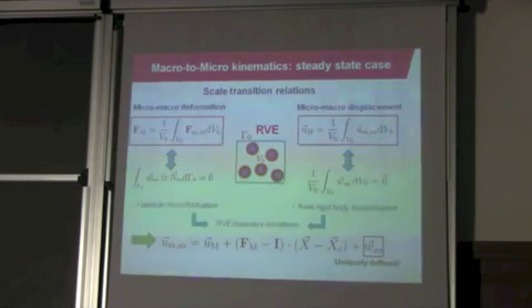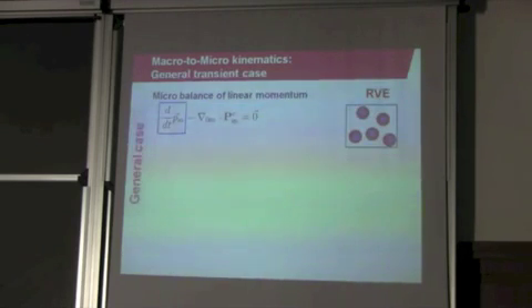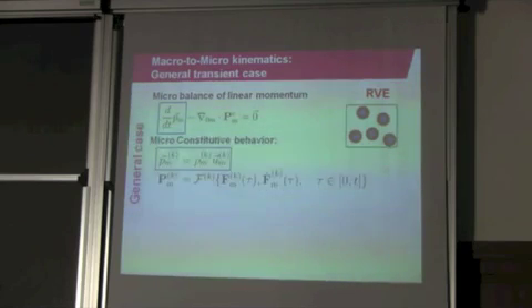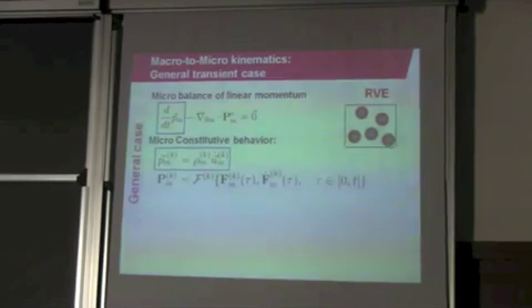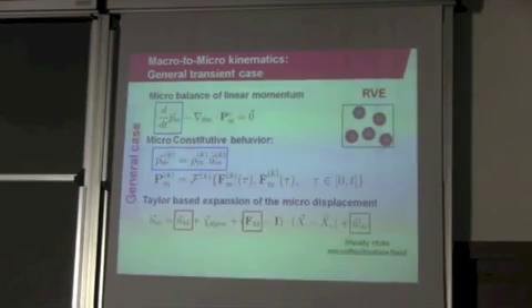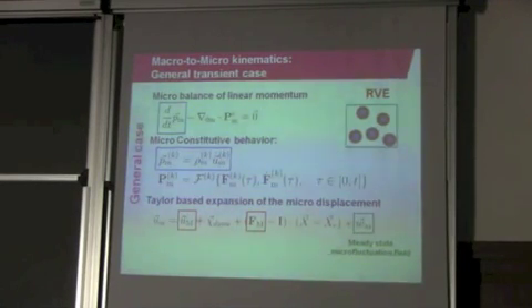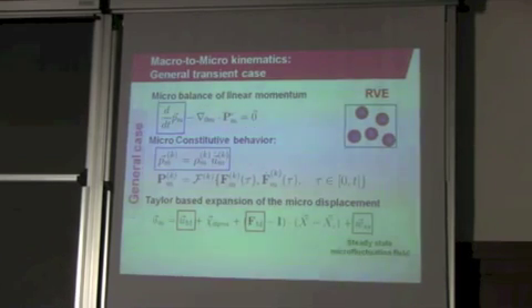Okay, fine. Now, what do we do if we are going to the transient case? Now we are solving the balance of linear momentum on the microstructure, meaning that in addition to the stress-strain constitutive laws, we also need the definition of the momentum, but this is just the usual normal continuum, nothing special there, so it's just the standard definition of the momentum. And now we do careful consideration of the micro displacement on the RVE, where we again have these two macrohomogeneous terms represented by macroscopic displacement and macroscopic strain. We have here this microfluctuation field, which we already know, which corresponds to the steady state of the microstructure, which is purely the result of the fact that it's heterogeneous.